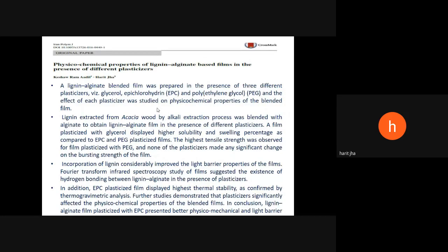Lignin extracted from acacia wood by the alkali extraction process was blended with alginate to obtain lignin alginate film in the presence of different plasticizers. A film plasticized with glycerol displayed higher solubility and swelling percentage as compared to EPC and PEG plasticized films. The highest tensile strength was also observed for a film plasticized with PEG, and none of the plasticizers made any significant change in the bursting strength of the film. So the strength properties were tested after using different types of plasticizer.